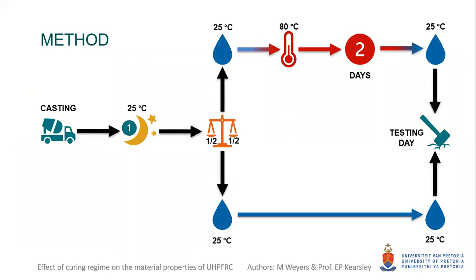The casting procedure and curing method that was followed is shown in the diagram. After casting took place, a curing blanket was placed over all specimens in a temperature-controlled room for 1 day. After demolding took place, half of the specimens were placed in a 25 degrees Celsius water bath, while the other half of the specimens were placed in a different curing bath.